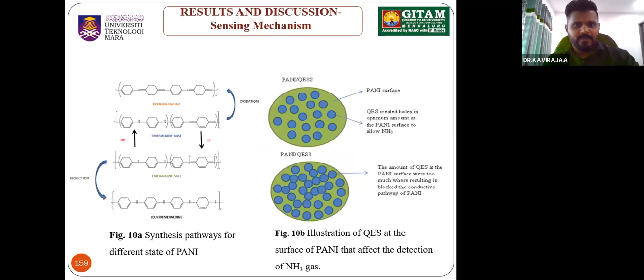Next slide. Figure 10a shows the mechanism where the polymer that we synthesized is green in color, and when we let it react with ammonia, the film will turn blue. That is another optical observation. Figure 10b, the one at the top, shows the optimum amount of eggshells in the PANI matrix, but the bottom one shows too much, for the PANI/QES3, where too much eggshell agglomerates and blocks the proper conductive pathway and also the reactive sites. Next slide.